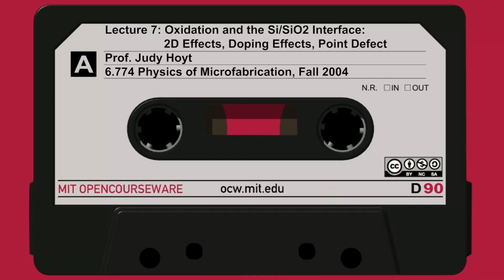They were trying to keep the oxidant from getting around. Remember, if we go back here, let me go back for a second. The starting structure here, the problem is that at this corner, the oxygen can diffuse straight in and right off the bat start oxidizing, and that's going to form where the bird's beak or the bird's head ends up. So they thought, all right, let me put this nitride mask all the way down the edge, and that'll keep the oxidant from going up there and reduce that amount of oxidation.